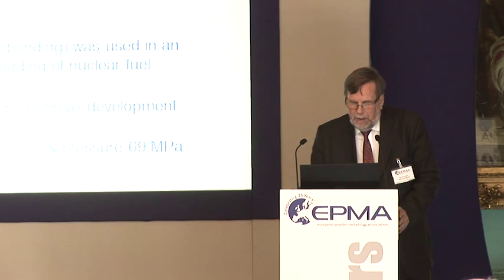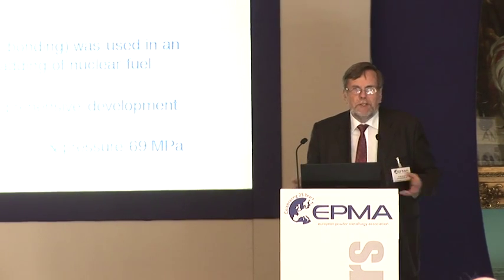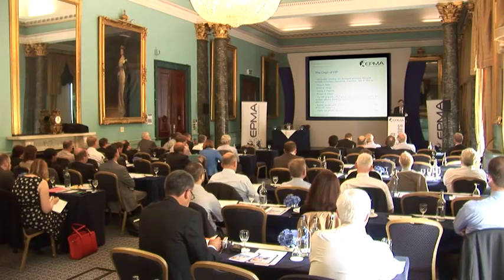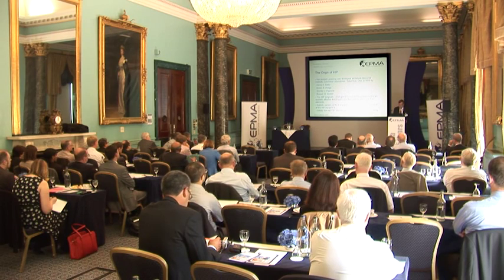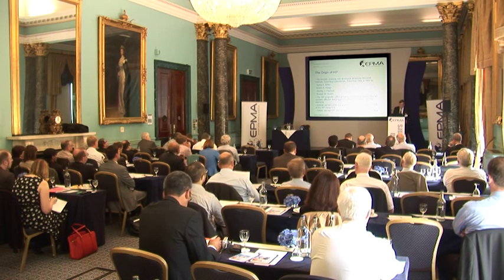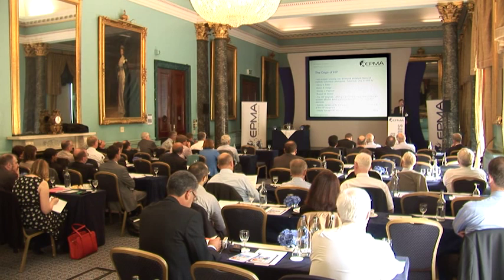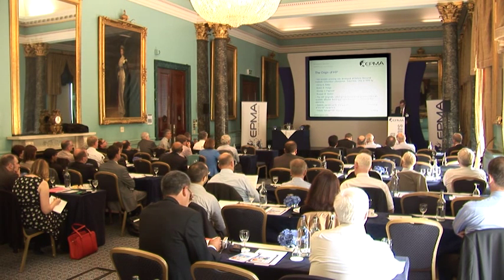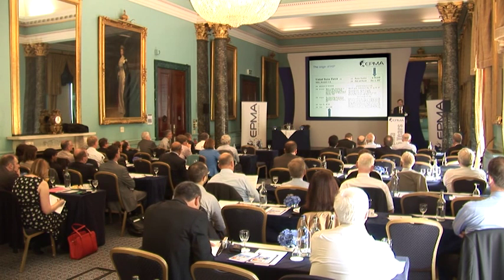both of semi-finished products and near-net shape products. And this process was in the beginning called gas pressure bonding, because we used it for pressure bonding of nuclear fuel elements. Initially, a hot wall HIP was used with a maximum temperature of 830 degrees centigrade, a pressure of 69 megapascal.